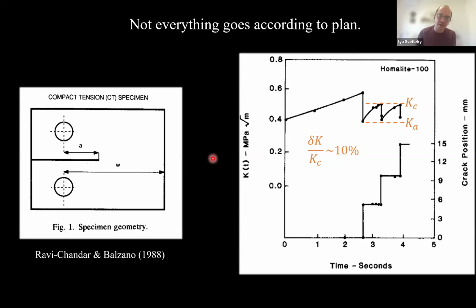I should have reached out to you to talk about that. I was thinking about it for very long. So the initial crack that Ravi-Chandar induces is not sharp. This is why the first point is indeed higher than the other ones. But once you created a sharp crack, and once the crack stopped, I'm not exactly sure why the crack will be blunted after the arrest, unless you have some smearing due to viscoelasticity or something like that.